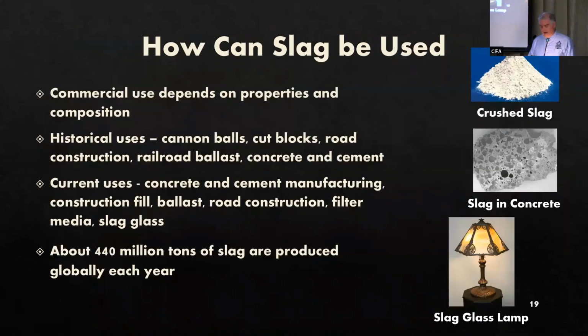So with all that slag, can it be used for some productive applications? Well, the answer to that is yes. Although the furnace workers considered the slag a waste, the slag could be used for beneficial applications. Even at Cornwall Furnace, even though we think most of the slag is present in that pile next to the furnace building, some of that slag was used as fill in the low-lying areas surrounding the furnace.